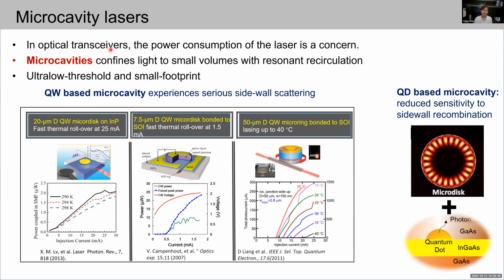And in optical transceivers, the power consumption of the laser can comprise a significant fraction of the total transceiver power budget. Microcavities can solve this issue, as they can confine the light to small volumes with resonant recirculation, and have the advantage of making ultra low threshold and small footprint light sources. However, these quantum well-based microcavity devices normally experience serious sidewall scattering and recombination as the resonator size is reduced to tens of microns. This can result in faster rollover, increased threshold, and a low operation temperature.